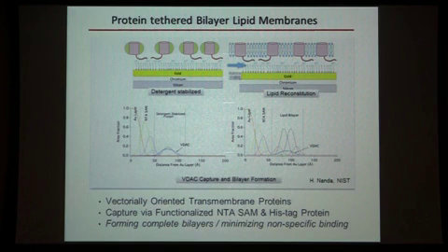Reflectometry measurements for the lipid bilayer actually fall basically on top of the VDAC protein, so you get scattering from the lipids and the protein, sort of suggestive of this model of the protein being basically embedded within a bilayer. And this is in the process of now being further validated that this has worked, but it again demonstrates the possibility to first generate these surfaces by immobilizing protein and then backfilling with lipids. And the power of the neutrons, again, to identify those different components selectively to say where we are.